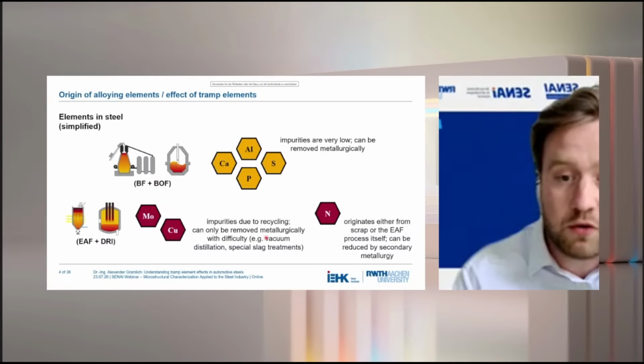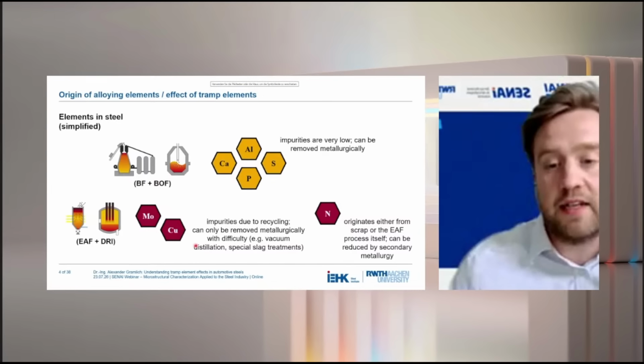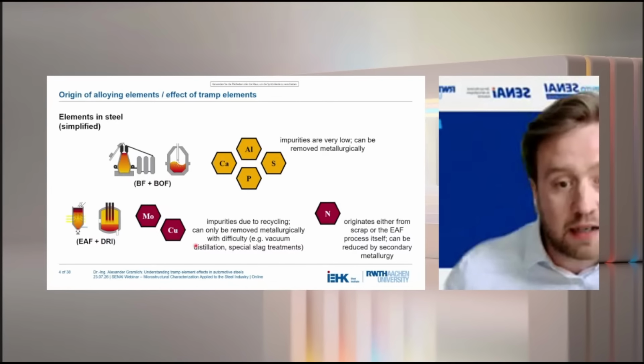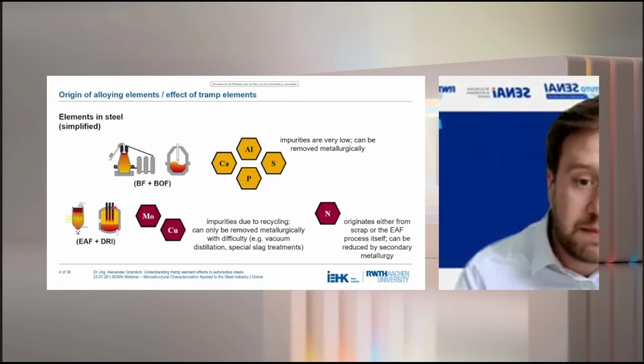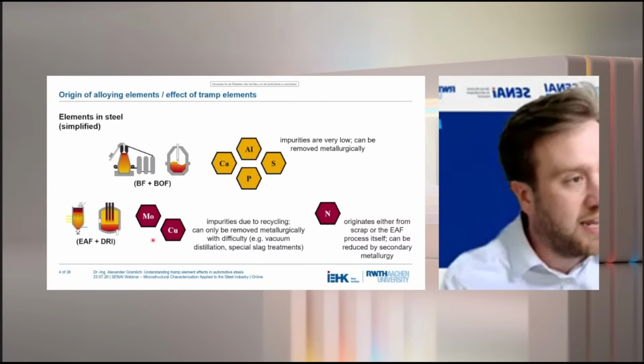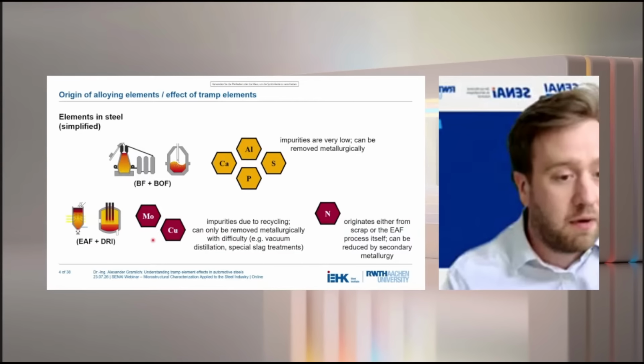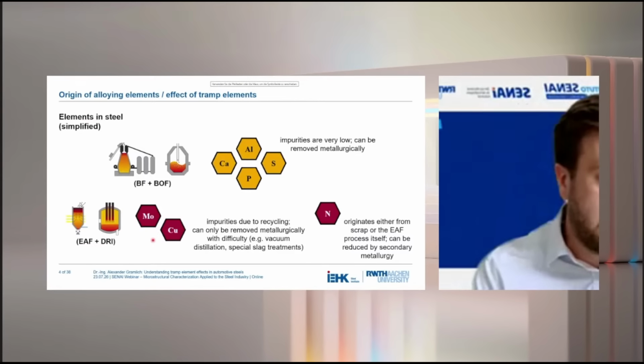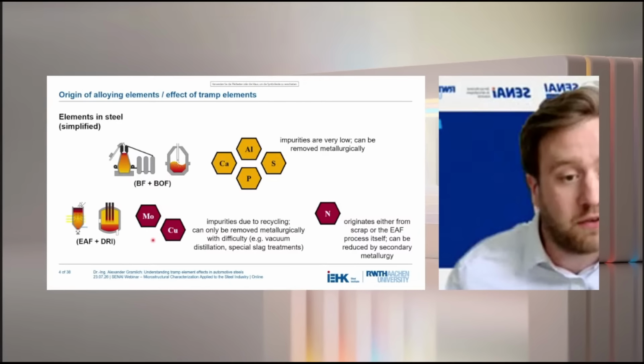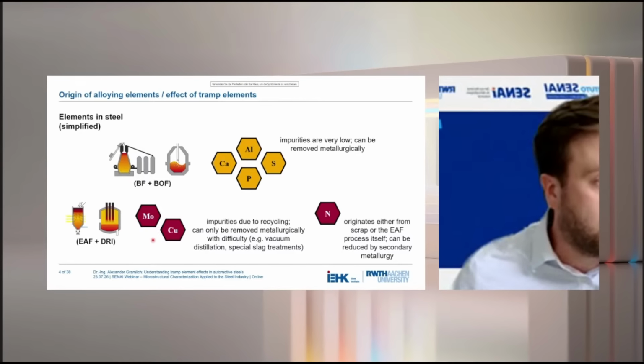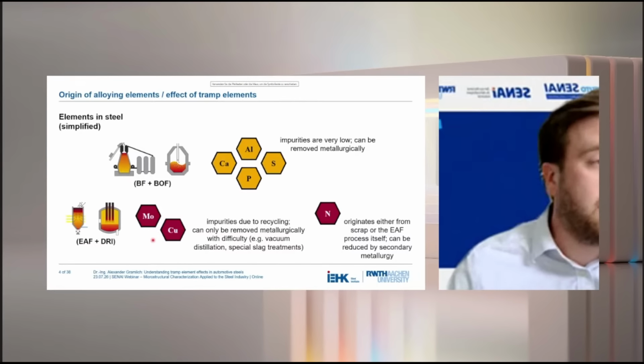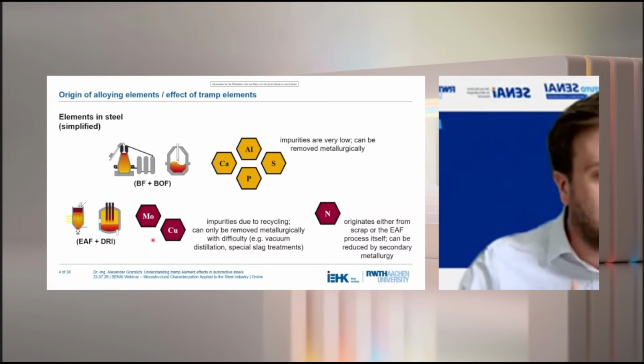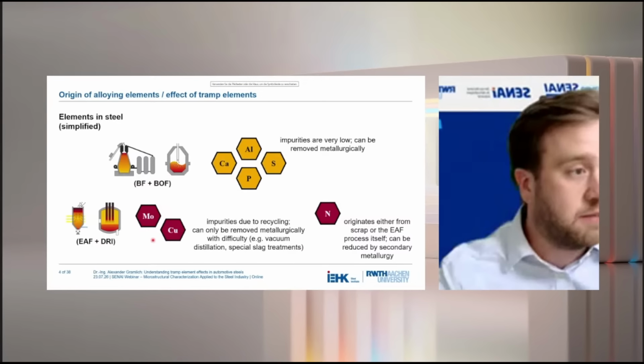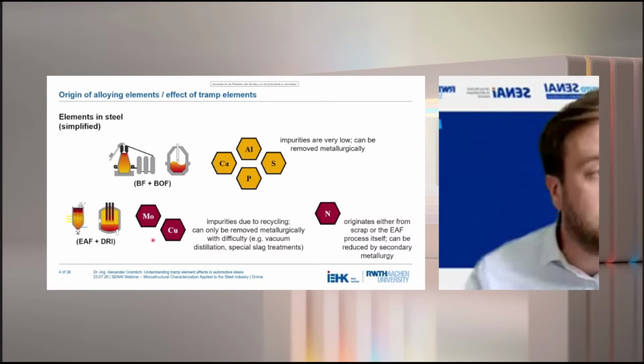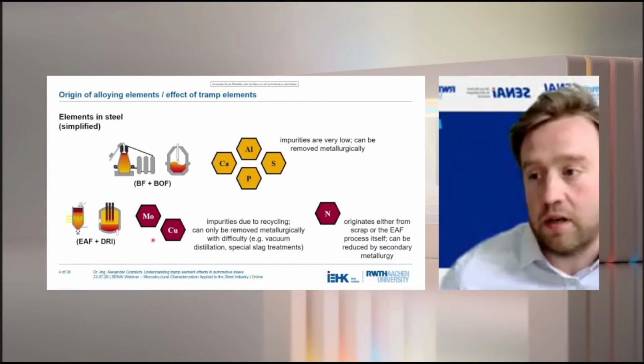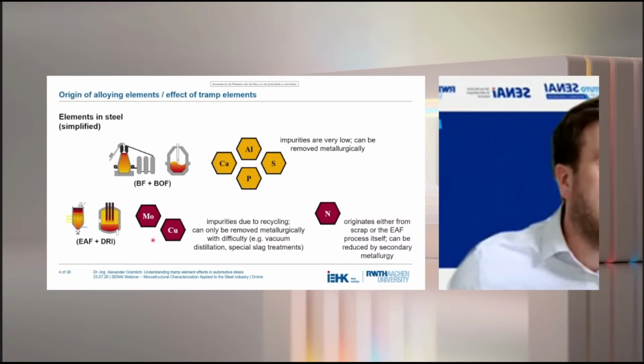When we are then going to future steel production, for example, mixing DRI with a lot of scrap in an electric arc furnace, we will introduce tramp elements like copper or molybdenum, which are enriched in post-consumer scrap, into our melt, and they cannot be removed very easily. There are some methods to extract, for example, copper. For example, vacuum distillation can remove a lot of the copper from the melt. However, all of these technologies which are available to reduce these tramp elements are very expensive, and you basically lose your business case for steel production if you would use this for, let's say, standard steels for construction, for example.